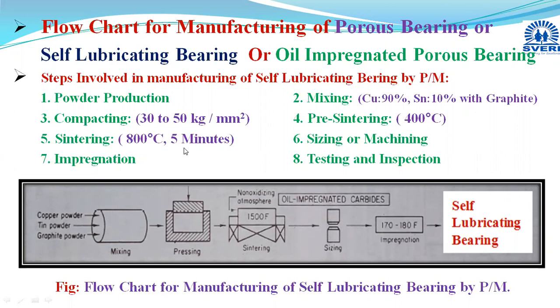Okay, and during this heating, what will happen? Diffusion will start. We have a mixture of copper and tin. Then these tin particles start melting. They will get converted into liquid state, and that molten liquid tin will get diffused on the copper. In this way diffusion occurs, and due to this diffusion, the particle size decreases and the amount of porosity decreases, which is termed as the densification of the component.